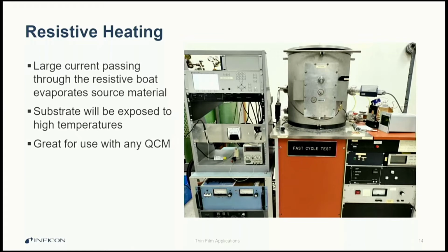Physically changing the material's phase in order to transport it from the source to substrate makes this a physical vapor deposition application, also known as PVD. One thing to keep in mind with resistive heating applications is that the substrate will be exposed to high temperatures. This can make the deposition onto a plastic or other temperature-sensitive substrate more difficult.